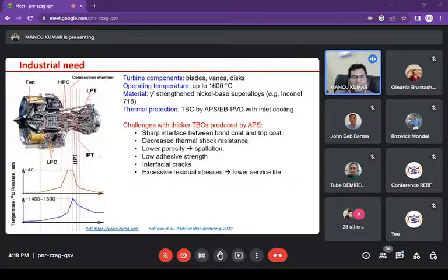A typical example I can cite is turbine blades in aerospace. In turbine blades, vanes and discs are the components where superalloys are used, and they are subjected to operating temperatures of 1600 degrees Celsius and above. So which metal can survive? Hardly any metallic material without coating assistance can survive in such situations. So they require thermal barrier coating, which we call TBC. These TBCs are produced by atmospheric plasma spray or electron beam PVD process with an internal cooling system. So there is a coating and also an internal cooling system to cool it down during the process.